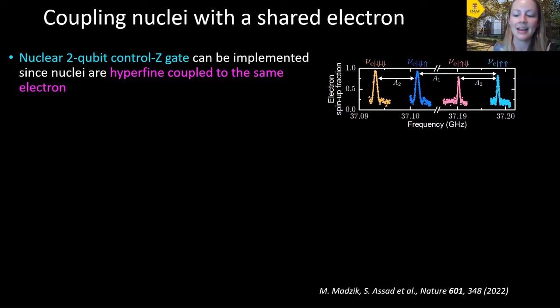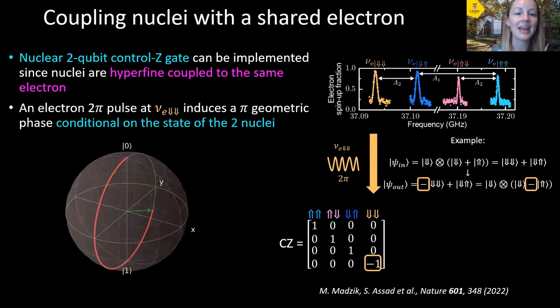And to do this, we can look at this small video. So when we apply a 2-pi pulse onto the electron, so you perform a complete rotation of the electron spin around the Bloch sphere at a particular electron spin resonance frequency, that will impart a pi geometric phase onto that particular nuclear state, which results in a minus sign. So for example, here, if we apply a 2-pi ESR pulse on the state which has the nuclei in a spin down down, then we'll get this -1 factor for this spin down down state. And this unitary matrix shown here is an example of a control Z gate. And so in this way, we can couple two nearby nuclei through this shared electron. And this work was demonstrated and published last year, which is very exciting for us.